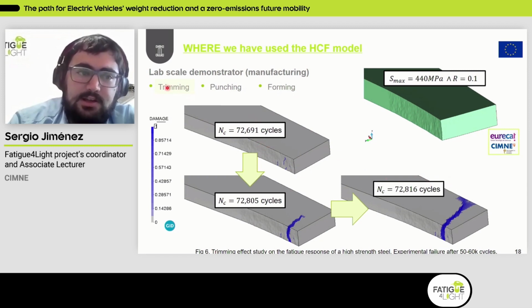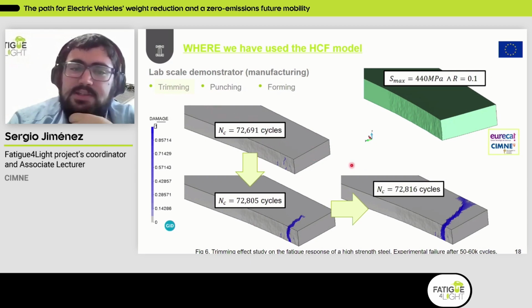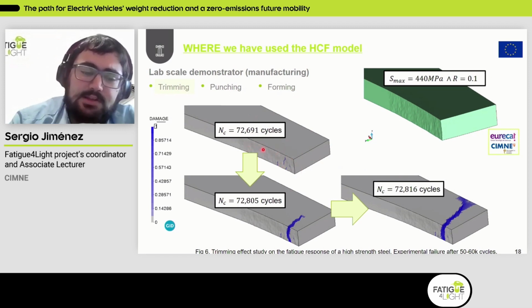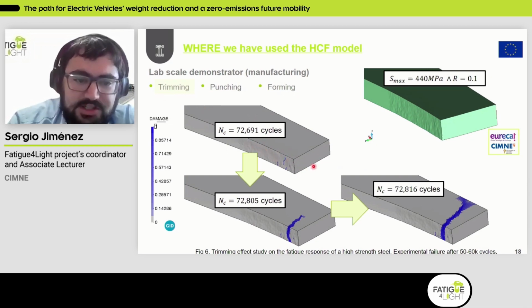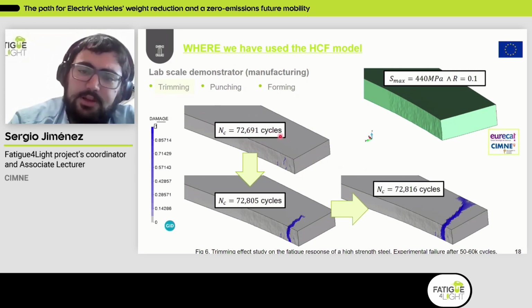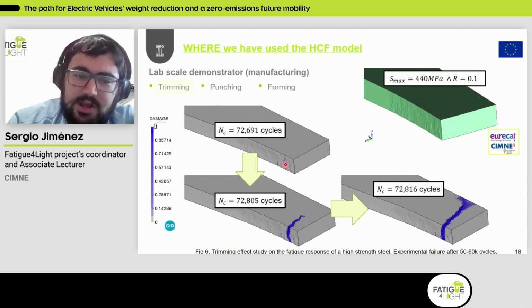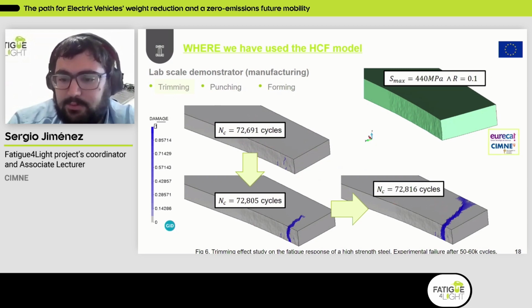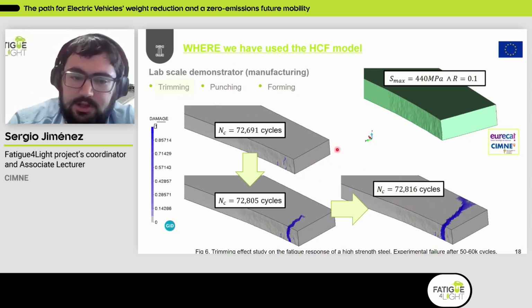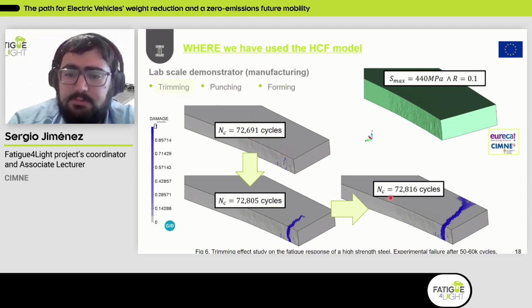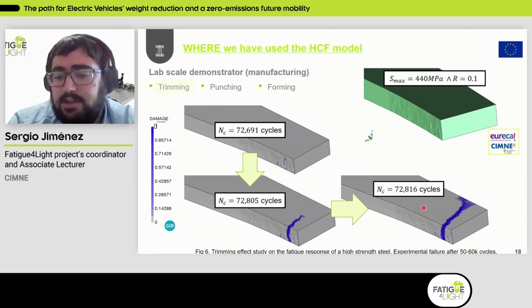effects. So basically, in this particular case for the trimming, what we've done is changing the roughness, the surface of these geometries, accounting for this change in roughness coming from the trimming process. And by doing that, this has an effect on the fatigue response in the material. So we have different patterns of crack observed, different amounts of cycles, and this correlates perfectly with the amount of cycles observed experimentally. We are not taking into account here residual stresses, and this may explain why we are obtaining higher values, higher fatigue life compared with the experimental results.